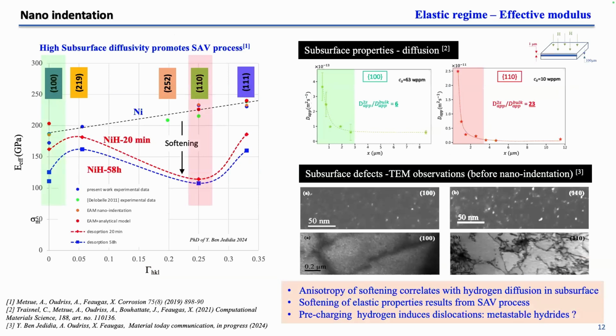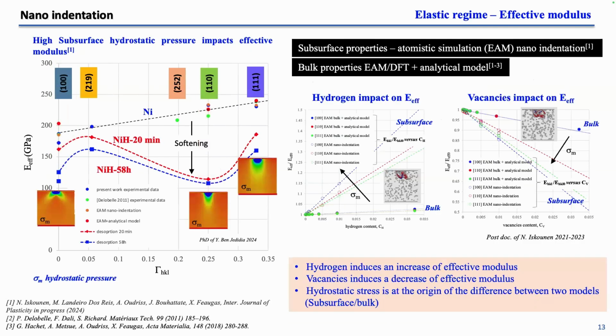The first reason is the fact that the main softening is obtained for the large diffusivity, the 110 compared to 100, and is directly linked to the production of defect, which shows that the vacancy concentration is higher in 110 than 100 when we introduce hydrogen. Another interesting feature is that this orientation will also produce dislocation, which means that probably we have produced metastable hydride, which disappears afterwards when we perform TEM observation.